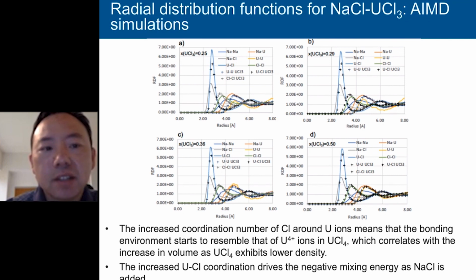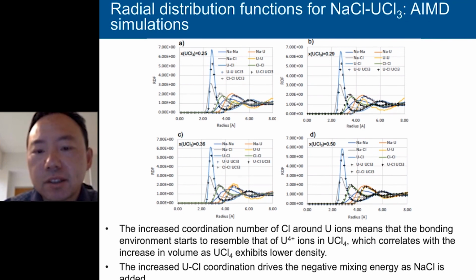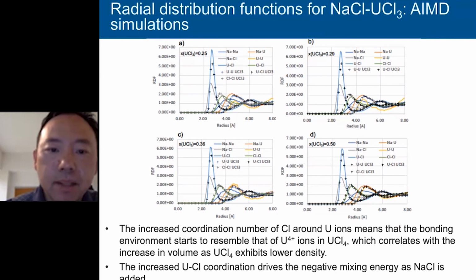Finally, David looked very closely at the radial distribution functions of one of the binary salts, and one cool observation is about the first peak, shown in blue. These are the interactions between uranium and chloride. In the molten salt, this peak is actually taller than the peak shown with the crosses, which is in pure uranium chloride 3. So you can see that there are more chloride surrounding a given uranium atom, suggesting that even though the original base salt is uranium chloride 3, the local environment of uranium is more like that in uranium chloride 4. This explains the negative mixing energies. David may have better explanations, so if there are questions, please ask David.